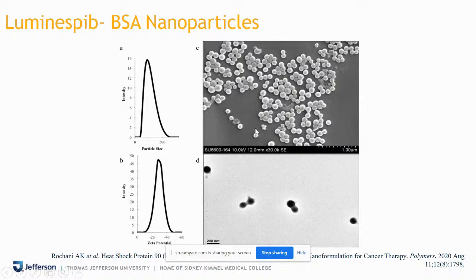We confirmed the size of these nanoparticles using SEM and TEM. Now you see the TEM of this thing is like black. It doesn't have those crystalline particles. This is the classical TEM image of a drug-loaded nanoparticle system. If you have inorganic metal particles like Fe3O4, or crystalline particles like gold, you can see a contrast happening in the TEM images. But here it's clean and clear.